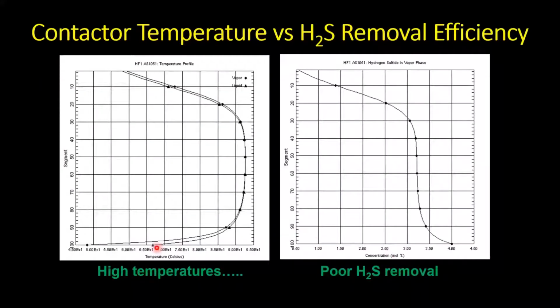This is from simulation. On the left-hand side here, this is a temperature profile inside an absorber. Now, typically we have a large temperature bulge at the bottom because we're reacting amine with lots of acid gas. We get a big exotherm. And then typically that temperature starts to cool down, and then it levels off as it goes to the top of the tower. In this case, we have a massive temperature bulge, way too hot.